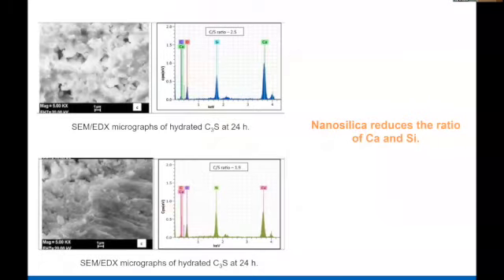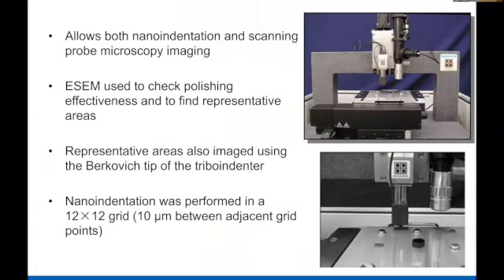approach. We also found, using the scanning electron microscope SEM with energy dispersive analysis, that the calcium to silica ratio is lower when we have nanosilica in the matrix as opposed to silica fume. And this means, if you do some molecular dynamics modeling, you can show that the lower the calcium silica ratio, the higher is the stiffness of CSH. And we proved that by measuring nanoindentation using the Hysitron nanoindenter. And the advantage of this is you can see where you are indenting, and so you can find out what is happening at different nano phases.